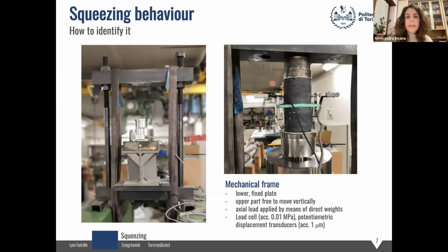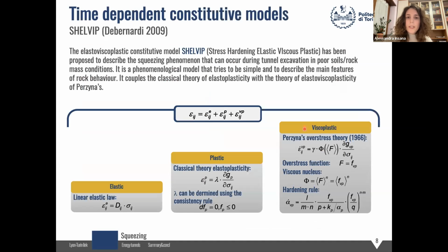Then another equipment is very simple, actually, and we used it because the other one was not available. And it's a mechanical frame, so very simple. We have a lower plate that is fixed and an upper plate that can move vertically thanks to a system of direct weights. And on this equipment, we performed an unconfined creep test that we'll see in a while, exactly on a sample of coal coming from SMP4 that I've described before.